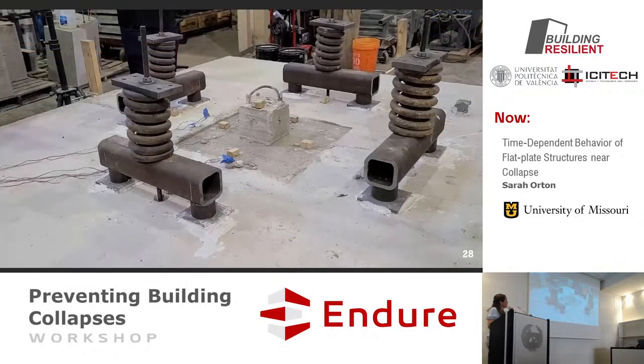And so this is a video. This was the test that failed in 20 minutes. We were loading it and watching it, and we noticed it was really soft. Every time we put on load, it just kind of went away. And they're like, well, I think this test is going to fail pretty soon. So we were able to record it.